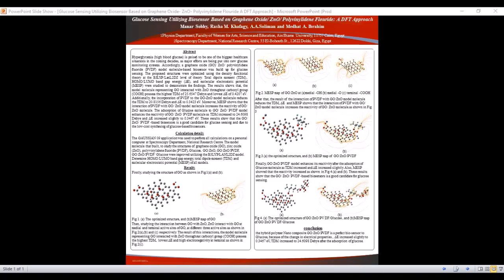Additionally, the incorporation of the polyvinylidene fluoride to a graphene oxide zinc oxide molecule reduces the total dipole moment and HOMO-LUMO band gap energy. Moreover, the molecular electrostatic potential shows that the interaction of the polyvinylidene fluoride with the graphene oxide zinc oxide model molecule increases the reactivity of the graphene oxide zinc oxide molecule.